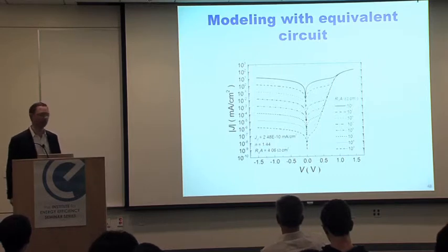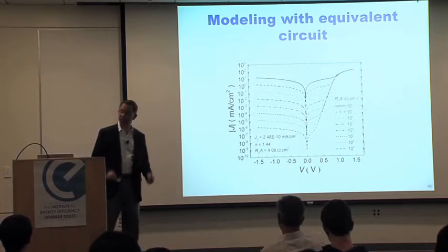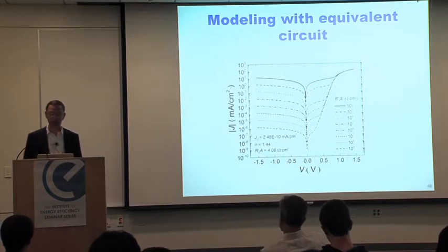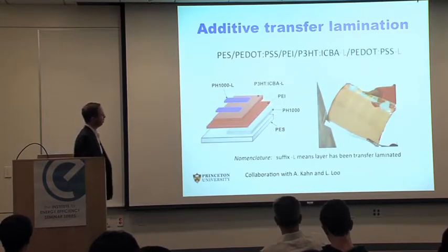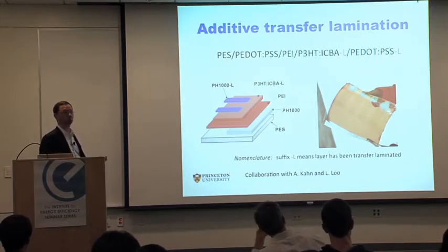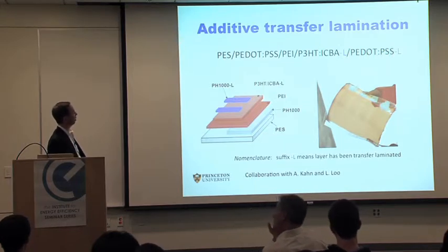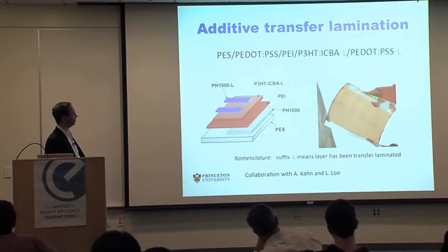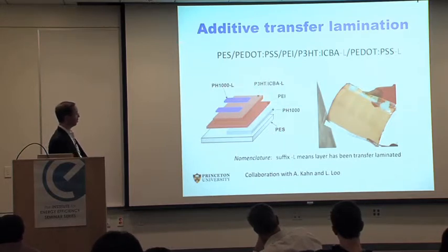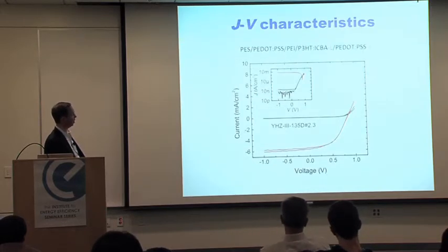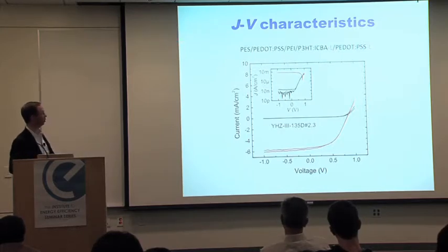Now, you might say, okay, you see that in very few devices, and it's not a majority of the devices. But actually, if you change the way you fabricate your devices, and here is an example of another all-organic or completely plastic solar cell, in which instead of using spin coating, we transfer laminate some of these layers. Okay, so the active layer is transferred from another substrate, and the top electrode is transferred also. And in layers like this, you consistently see a very high shunt resistance, and sometimes you can't even resolve the shunt resistance because it's below the detection limit.